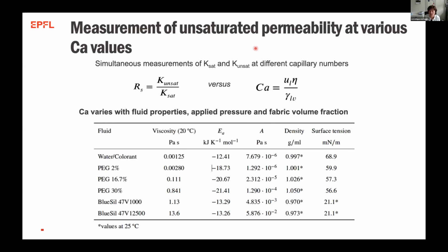We tried to do unsaturated permeability measurements with these same fabrics. For that, we varied the capillary number a lot, just to see what we measure. To vary the capillary number, we also varied, of course, the velocity, but it's a bit tricky to vary it beyond a certain extent. So we also varied eta and gamma. We used water, PEG (polyethylene glycol) solutions, and then silicone oils, so that we get a range of viscosities and, of course, a range of surface tensions that we need to take into account.